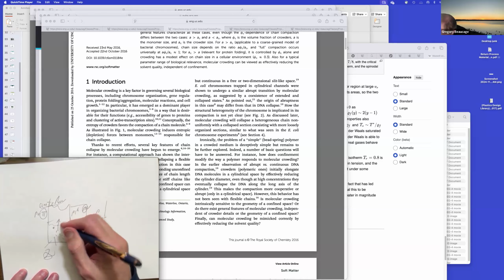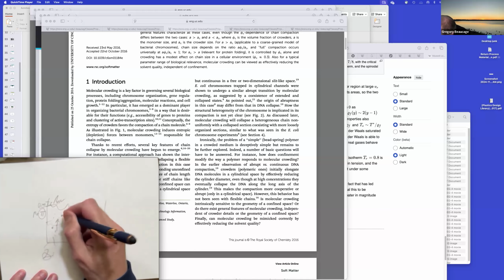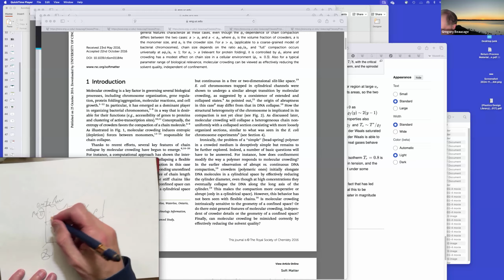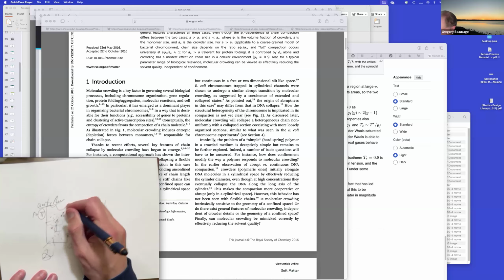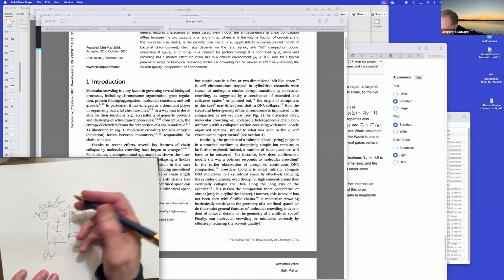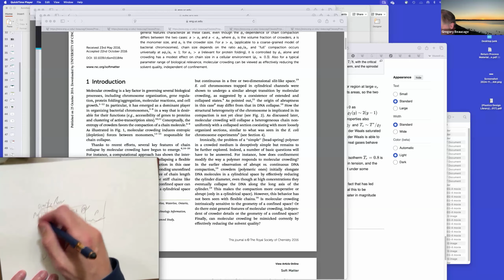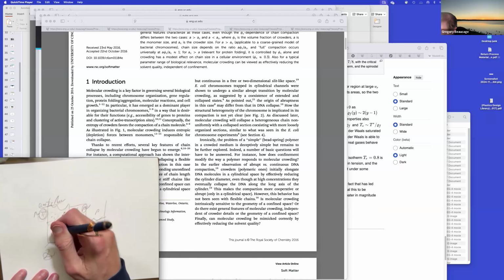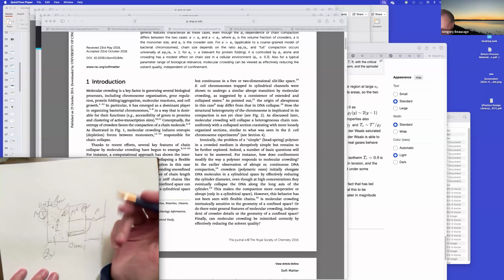Another way to look at this is you can think about each of these little polymer chains as having kT energy, flying around. Then this becomes just like a gas. So these little colloidal particles are acting like a gas, and they have a pressure pi, an osmotic pressure pi. So there's an atmospheric pressure, and there's this other pressure pi that has to do with, if you could ignore the water and just have the polymer things floating around with kT, they would have that pressure.